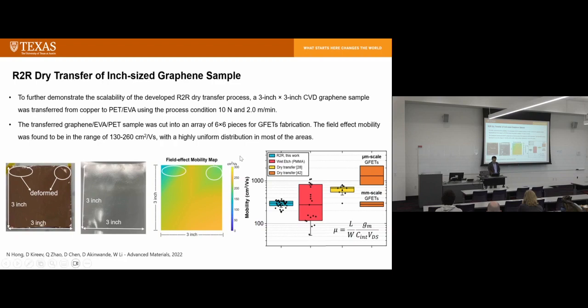Electron mobility is an important characteristic for electronics. We compared our mobility value with wet transferred mobility values. You see the roll-to-roll, this work, is right in the middle of wet transferred. So comparing the charge mobility itself, wet transferred samples and dry transfer roll-to-roll samples are very much comparable. And our sample has better quality because within the center, the variation is smaller. But if you look at the dry transfer samples, where people use small samples to do a dry transfer peeling experiment, you can get higher mobility values. This is from one of the studies, a little higher mobility values, just using small size graphene samples.